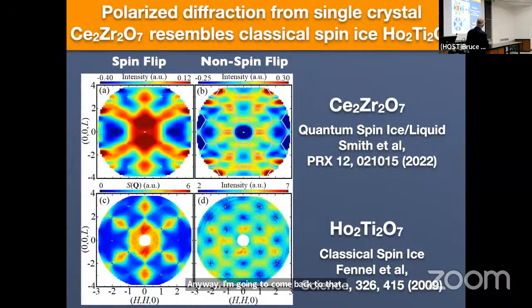This is another neutron scattering experiment, but a different one. The ones I showed you before were neutron spectroscopy. We had energy resolution. Here, we don't have energy resolution, but what we do have is a polarization dependence to a diffraction experiment. Okay, so we're doing two different diffraction experiments on the same material at the same time. So we're looking at neutrons where we control the polarization of the spin. It's going to come in and scatter off the sample either with a spin flip or without a spin flip. And you get two quite different structure factors, which are shown here. And what's interesting is that the non-spin flip structure factor still shows diffuse scattering, but the diffuse scattering is organized around the face-centered cubic zone boundaries that are appropriate to the pyrochlore lattice. Okay, so these are measurements that we did relatively recently on cerium zirconate.